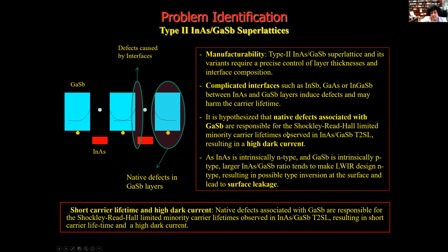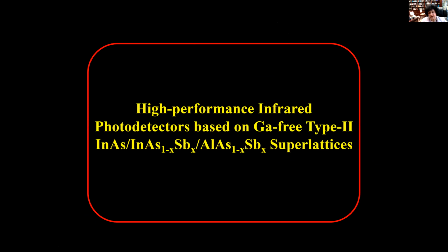But they say that it is not easy to do for production, especially when we go to the MBE and we need to have the 1,000 and 1,000 monolayers, very thin layers. So we came with the following, in order to eliminate all of the problems with the gallium antimonide type II binary, and to come with the gallium-free type II superlattice: indium arsenide, antimonide, aluminium arsenide. What is the problem of the gallium?